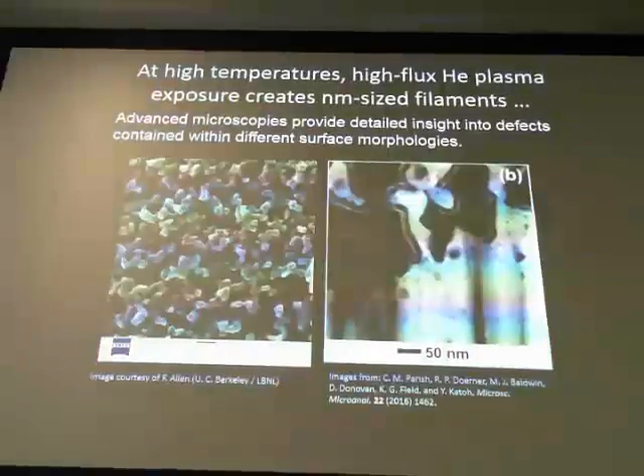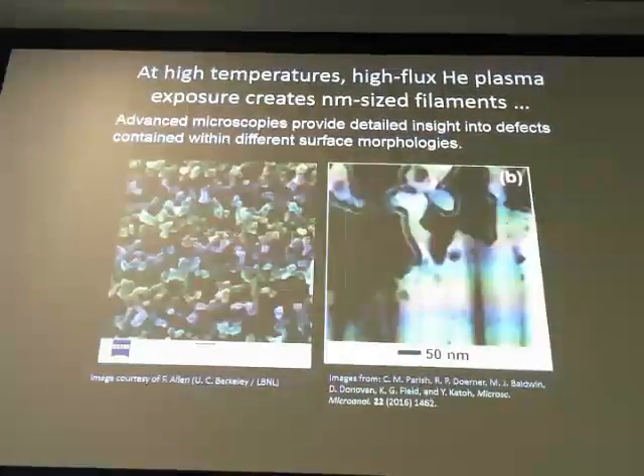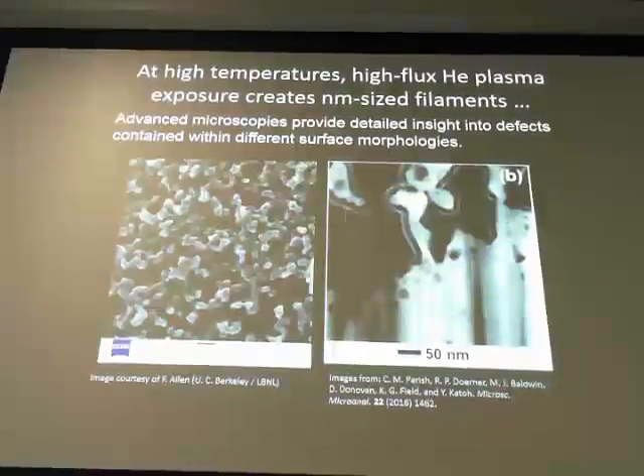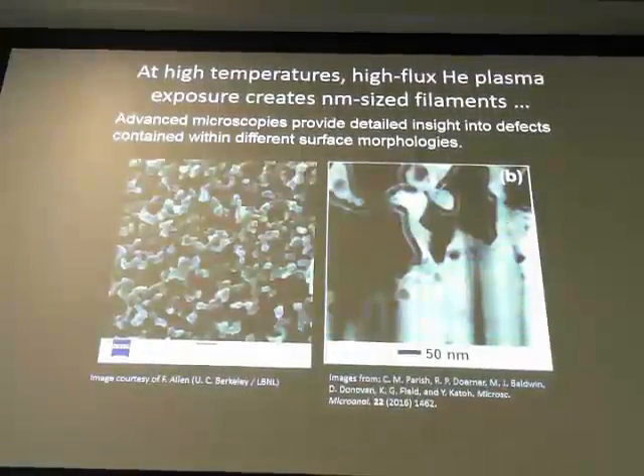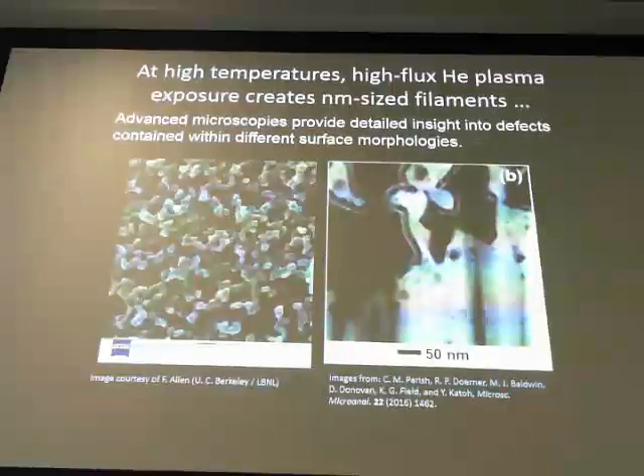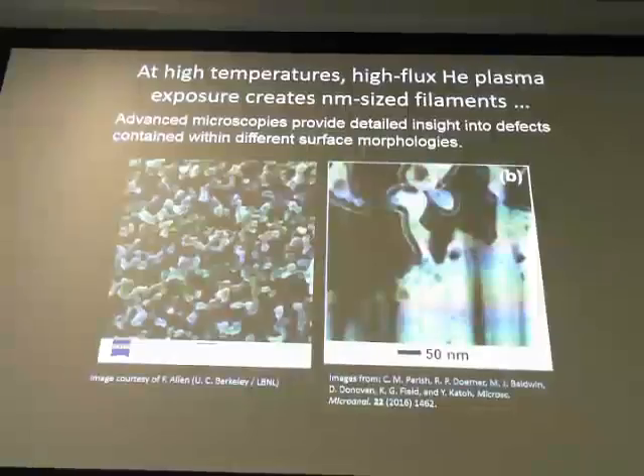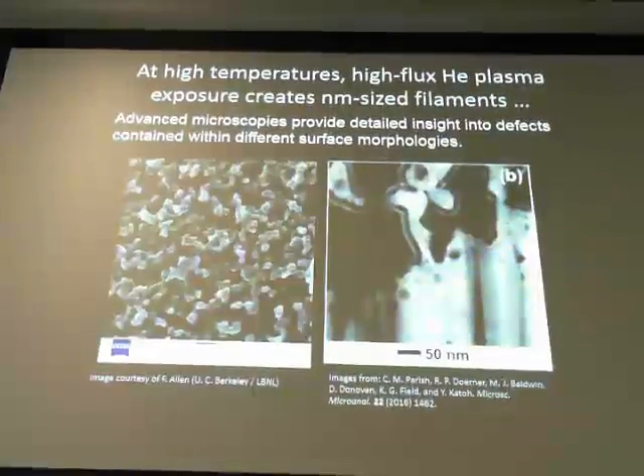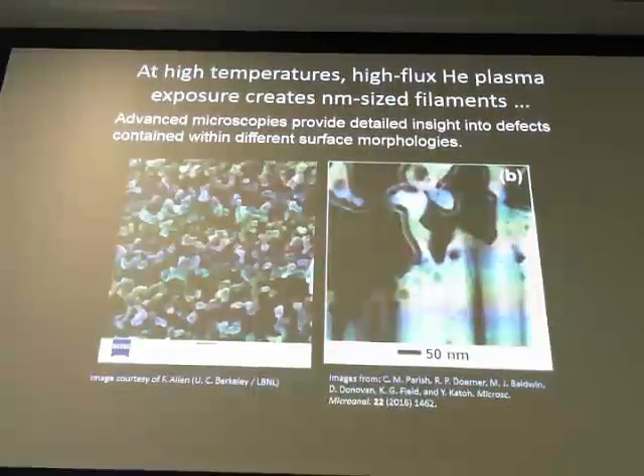Yeah. My problem with this compared to the reactor is that oftentimes people end up using a beam that goes in, and the real plasma is Maxwellian, and it has a lot of grazing incidence. And then the bubbles are slow to form. I just remember Manfred Kaminsky got it wrong years ago. Remember, he was the guy at Argonne, and he blistered the materials because he had a Bragg peak. I wonder if you might consider that.